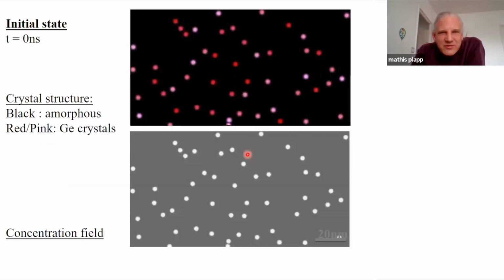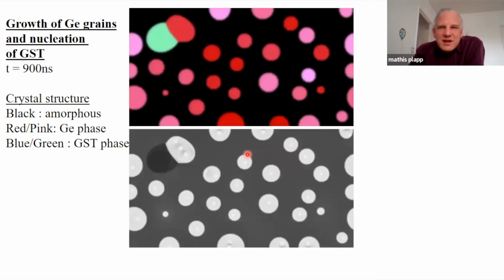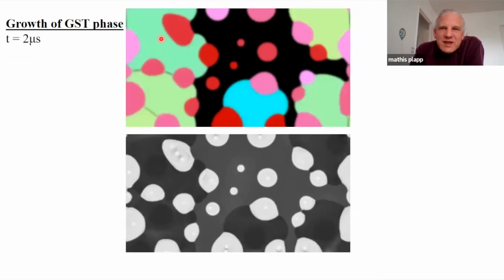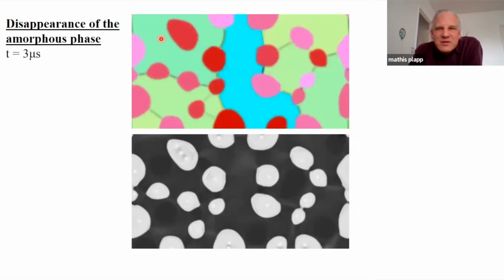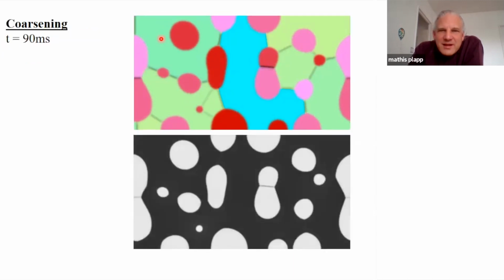So here's the sort of initial state. We have various grains of the germanium phase with different orientations. So all the different hues of red and pink are different orientations of this phase. Then the phase grows until here, the first bluish thing is the first grain of the GST phase. Then we have nucleation of other grains. So you see that they rapidly engulf the germanium grains and form grain boundaries. Then the amorphous phase is completely consumed, and we have a polycrystalline polyphase material. And this then coarsens with time.